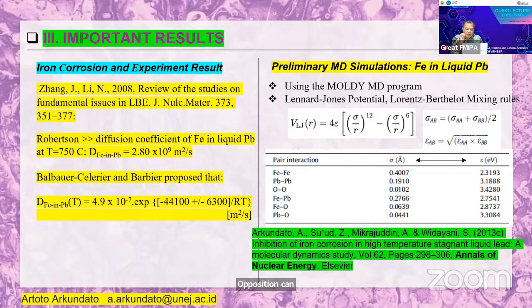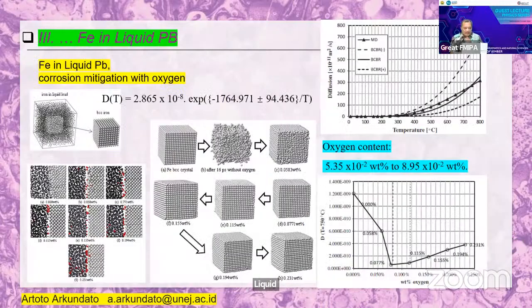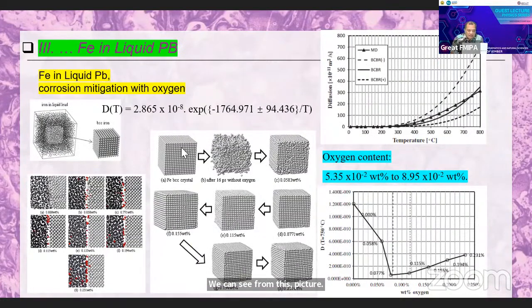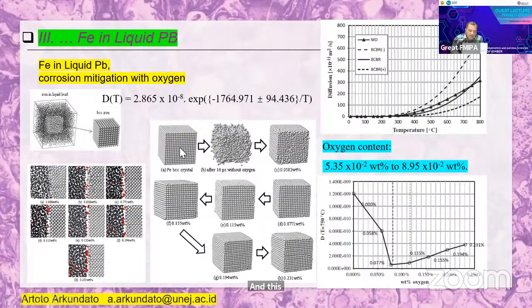Oxygen can reduce corrosion very well if we use pure iron in the liquid lead. We can see from this picture. This is the picture before simulation. This is the BCC, body-centered cubic, crystal structure of iron before simulation. After simulation, there is very high corrosion caused by liquid lead, like that.